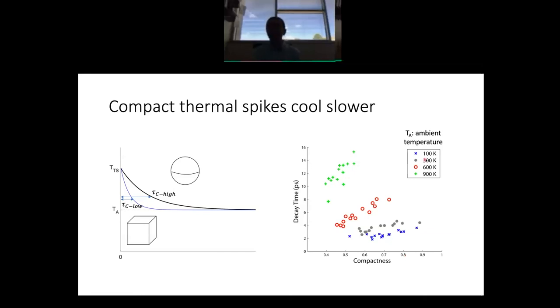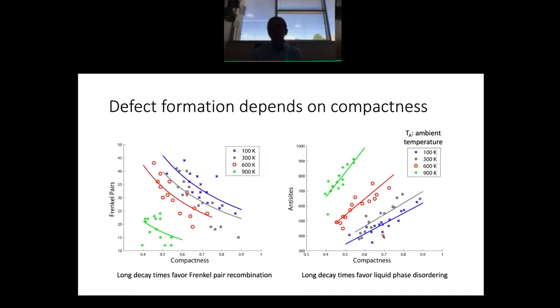So this plot here is showing you simulations that were carried out at a variety of different ambient temperatures, right? So we used ambient temperatures ranging from 100 to 900 Kelvin. This is the 900 Kelvin case. You can see that compactness is high, decay time is large, compactness is low, decay time is lower. And of course, the ambient temperature also influences the decay time. The lower the ambient temperature, the lower the decay time, because the thermal transport is faster. Okay? And what effect does that have on defect production?